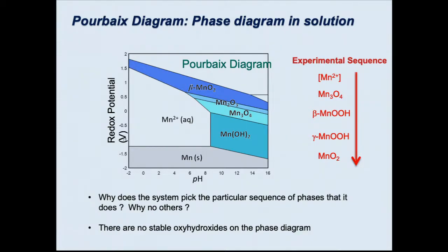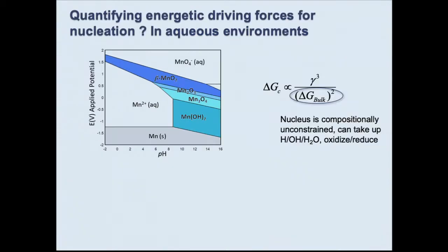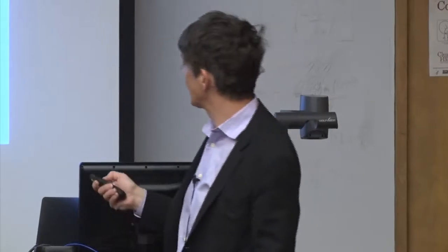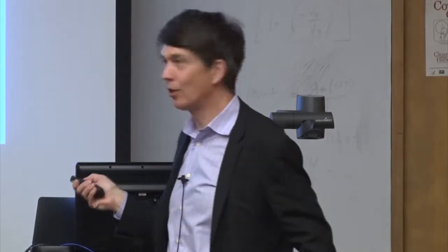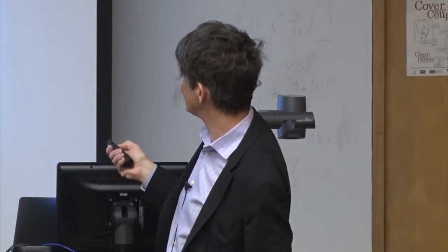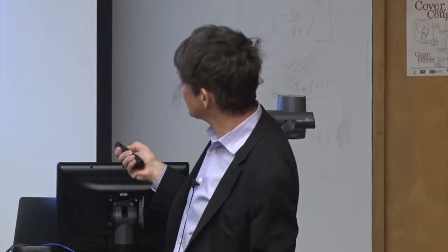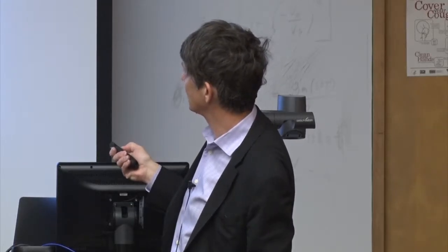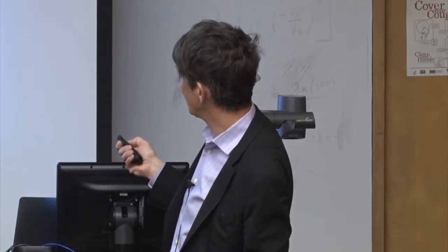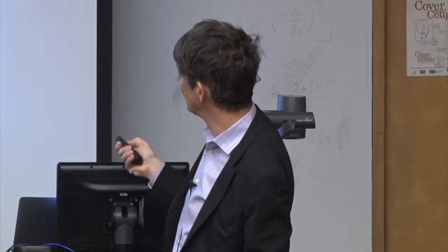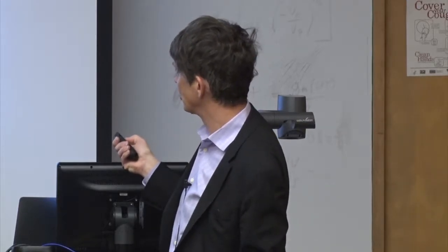So the first thing to do, to do this quantitatively, is to build the right thermodynamics, right? And if you passed your qualifying exam in materials science, you know nucleation theory. That's the classic question. If you do kinetics, that's the one question they always ask. Nucleation theory tells you that there's a critical activation energy for nucleation, which is proportional to the interfacial energy cubed and inversely proportional to the bulk driving force squared.